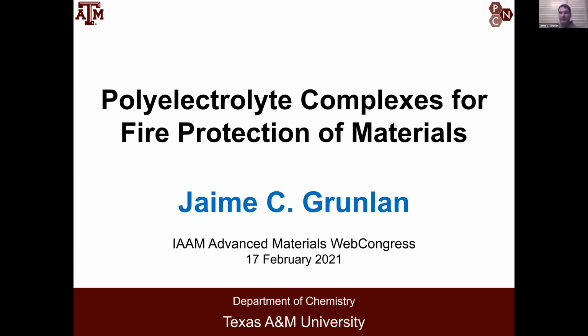In terms of the layer by layer assembly, it's a water-based coating method where we take cationic and anionic ingredients and deposit them from water into these very thin layers. The criticism of this technology is that it's a multi-step deposition process, sometimes tens of steps or even hundreds of steps to build the functional coating that you want.